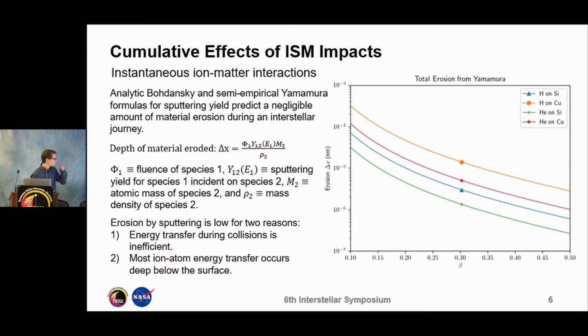So the analytic Bohdansky and semi-empirical Yamamura formulas are appropriate tools to discuss things such as sputtering and material erosion in a spacecraft like this. In this expression here, we have the depth of material eroded as predicted from the semi-empirical Yamamura formula. Phi is the fluence of the incident species. Fluence is the integrated flux, so it's the total amount of impacts per unit area over the entire duration of the mission. Y is the sputtering yield.